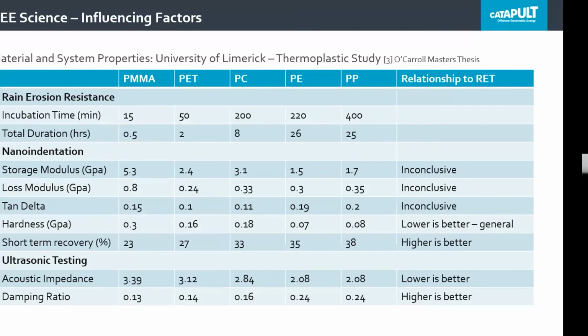Moving on to more laboratory-based testing, the University of Limerick, Anthony O'Carroll in his master's thesis, did a fantastic study correlating different thermoplastic materials to rain erosion resistance in their rain erosion test rig. From left to right you can see increasing rain erosion performance. First of all, you can see incubation time, which is the time to first see some erosion damage, whereas the total duration is usually the time before you actually see the composite material. He found that polyethylene and polypropylene have much better rain erosion resistance.